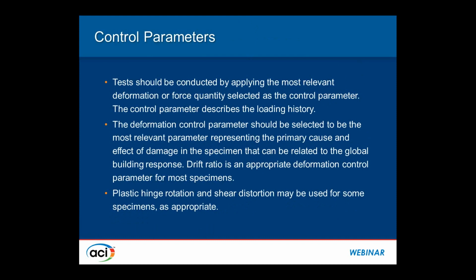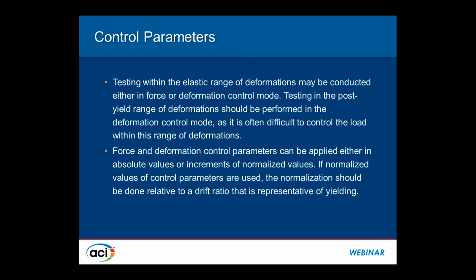During testing, the control parameter is very important. Again, we should select the control parameter that can be linked to performance levels. Here, a commonly used control parameter is drift, as would be the case in typical flexure dominant members, but one can choose to use, if it's a shear dominant test, shear yielding or shear capacity as a control parameter. But often, if you are testing a well-designed specimen, drift will be a preferred quantity that can easily be linked to performance indicators, which are linked to damage levels.